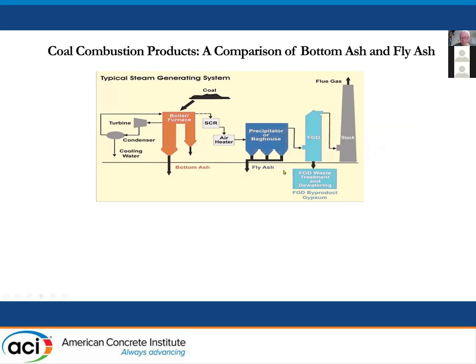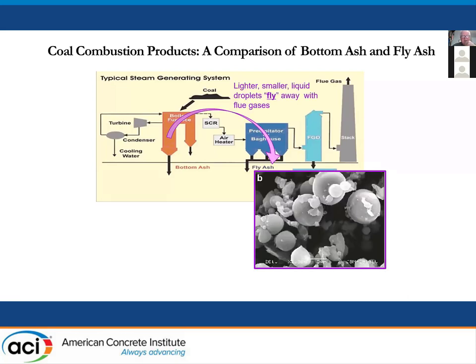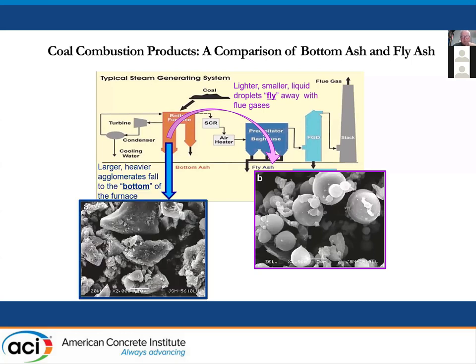So this is a typical plant, which shows the furnace in orange there, and the fly ash gets carried away in the gas stream. The bottom ash falls out of the bottom as bigger particles, and you can see they're not spherical because they were bigger particles. They didn't fly off into the gas from the liquid, so they didn't form nice spherical particles. They fall into the bottom, and they're typically much coarser.